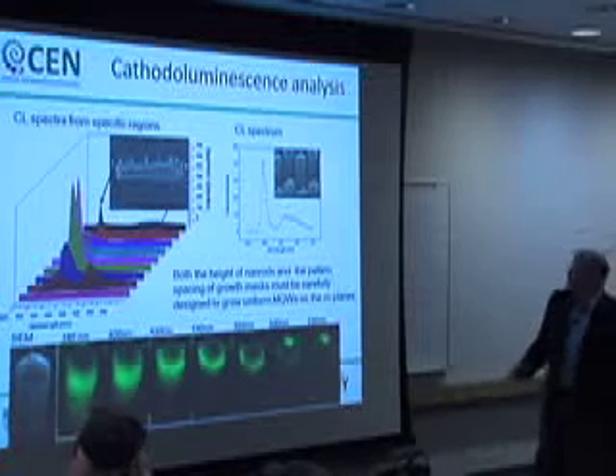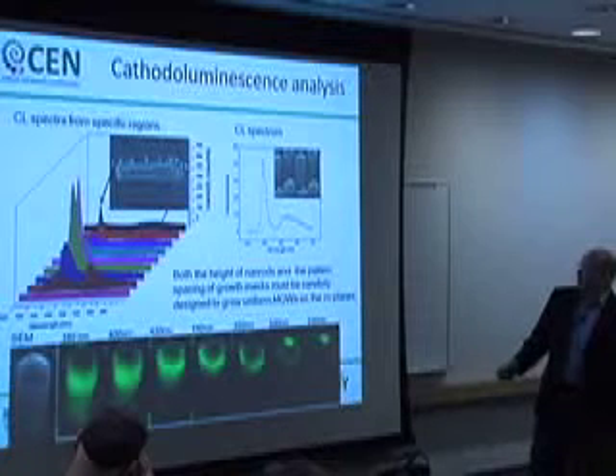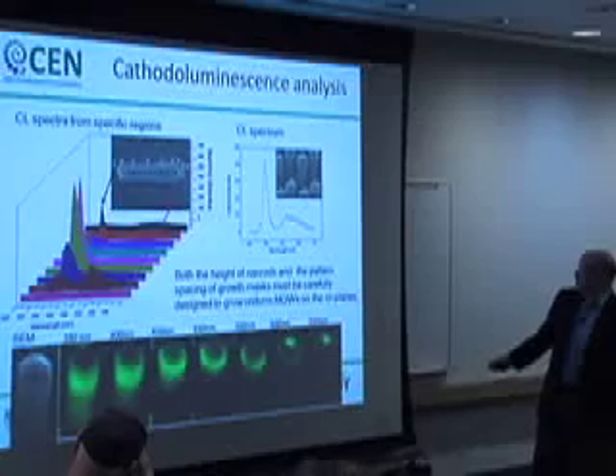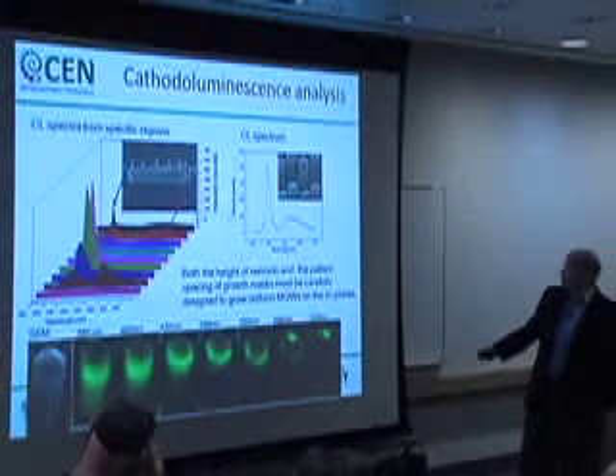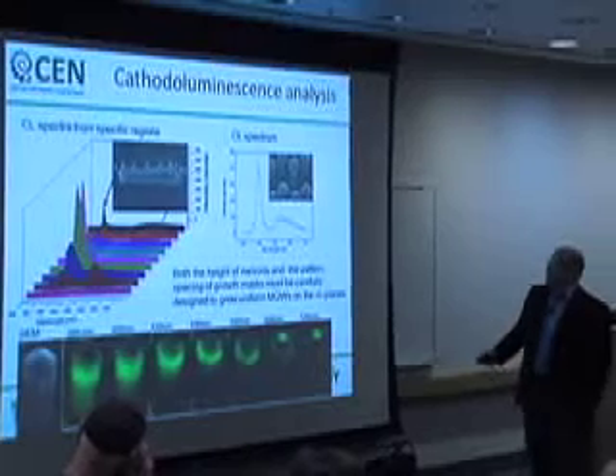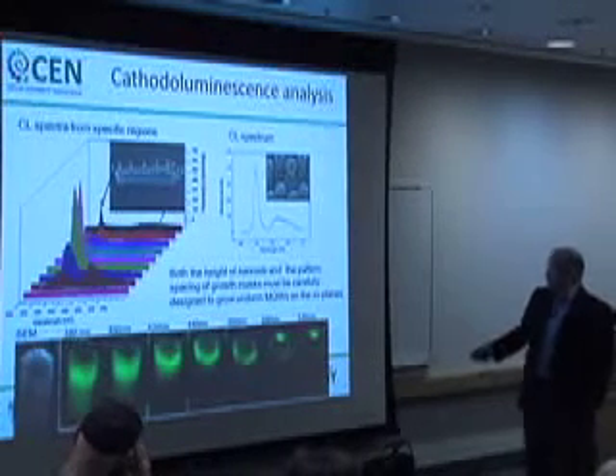On the other hand, we have seen some in which we didn't efficiently pinch off the C-plane, where we get fairly non-uniform growth, and we actually get a chunk of long wavelength emitting material up here at the tip of the nanorod. So we're working to understand the kinetics of growth to make sure that we understand how to control that and to eliminate it.